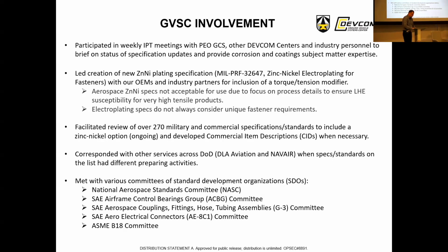So GVSC involvement. As far as GVSC involvement, we crafted MIL-PRF-32647. We worked very closely with subject matter experts from BAE, GDLS, from industry, and also within the military. The MIL-PRF-32647 added torque modifiers K16 and K20. K16 is the direct replacement for cadmium-plated parts, while K20 was the direct replacement for parts with zinc nickel plating with hexavalent chromium. Those K-factor controls were needed, and it allowed the Army to create threaded parts that can be drop-in replacements for legacy cadmium and zinc-plated parts. Without this, the Army would need to have altered torque tables for the assemblies involved, which would have been an even larger undertaking.